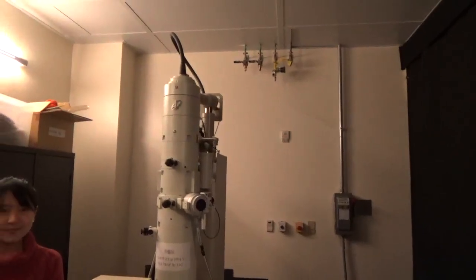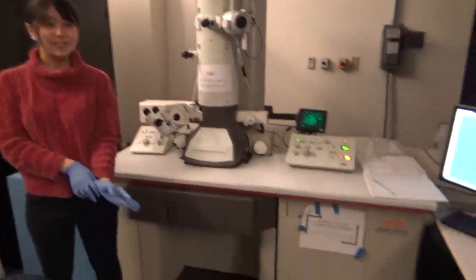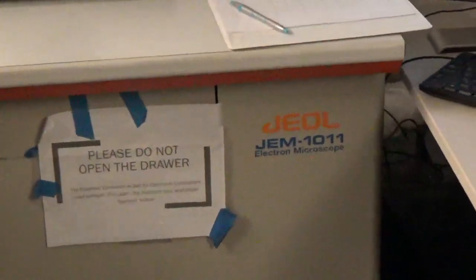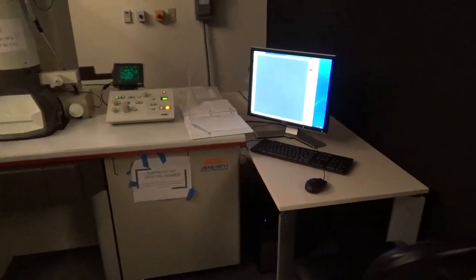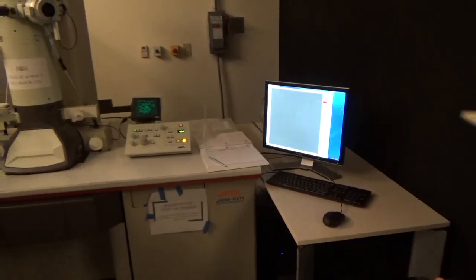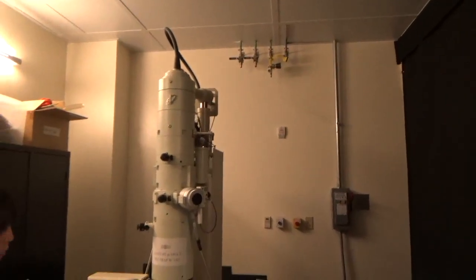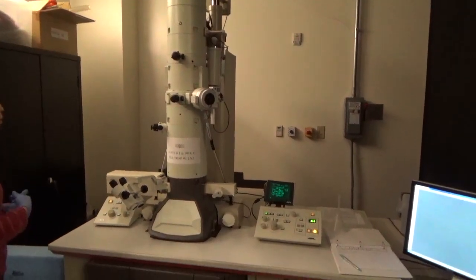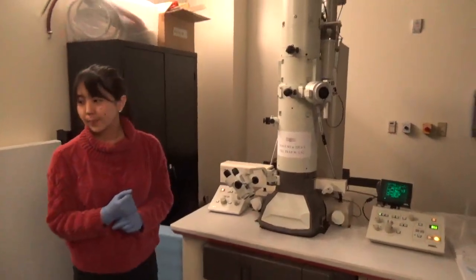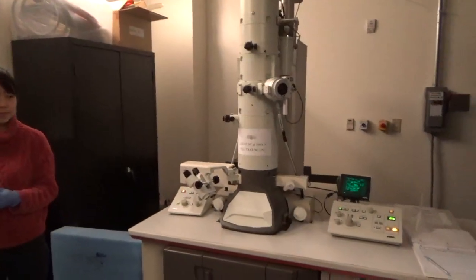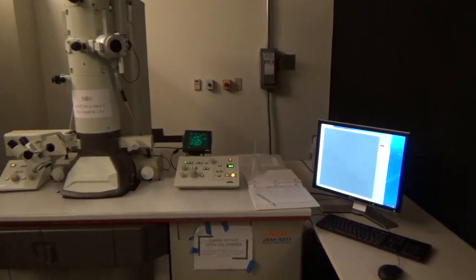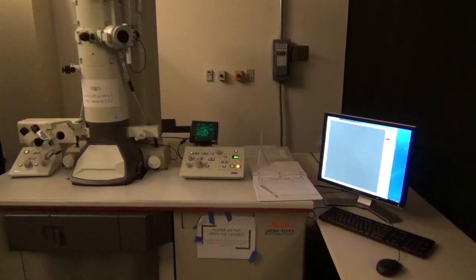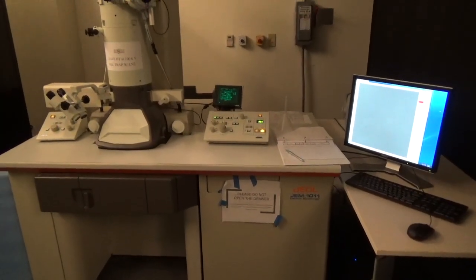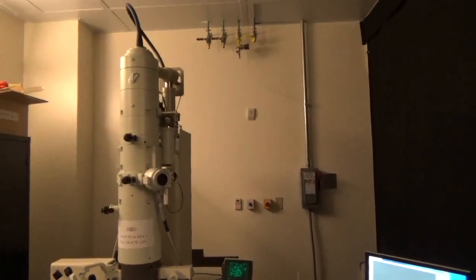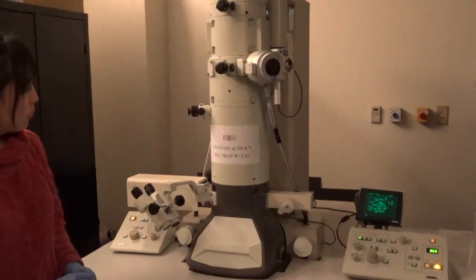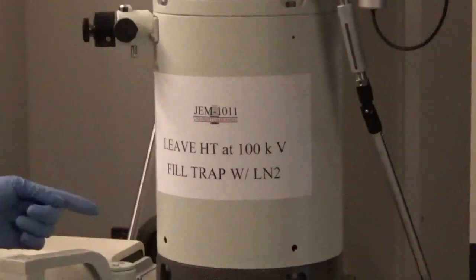This is a transmission electron microscope. It's a JEOL JEM 1011 electron microscope. It's a transmission electron microscope, meaning that the beam transmits all the way through the sample. And the picture you get from that will be a two-dimensional picture, and that will be different than the three-dimensional picture that we'll get with a scanning electron microscope. So this microscope has a resolving power of 0.2 to 0.4 nanometers, and it has an accelerating voltage of 100 kilovolts. So that means that there is 100 kilovolts that will be coming down from the top, going through the whole microscope and into the sample.